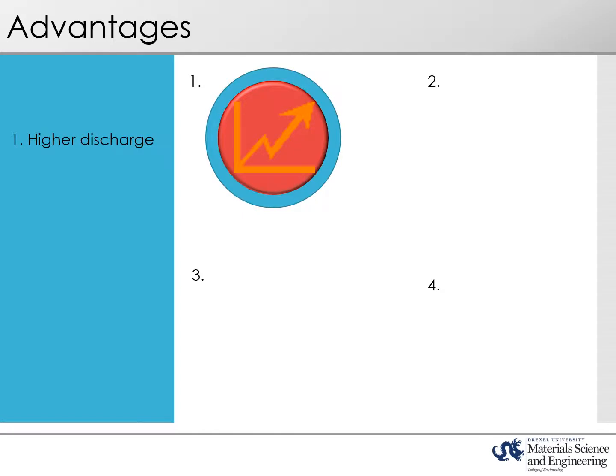LIBs are the most important and widely used rechargeable batteries because they operate with high reliability. Lithium-rich layered oxides are no exception, with the primary advantage of materials having a higher discharge capacity between 200 and 220 milliamp hours per gram and energy density, as they represent a significant improvement over most common commercial LIB cathodes, such as lithium cobalt oxide and lithium manganese oxide, LiMn2O4.